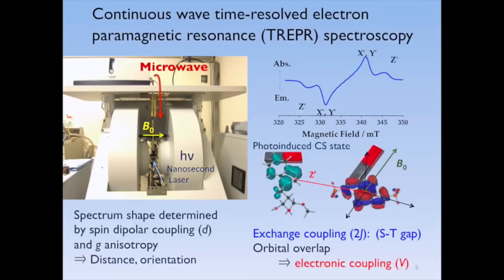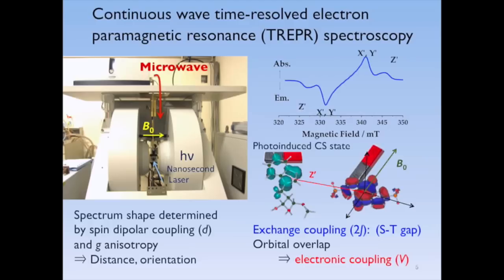The EPR spectrum is also affected by the singlet-triplet energy gap determined by the unpaired orbitals in the charge-separated state. Therefore, from the ST gap, one can determine the electronic coupling of the separated spins. In this perspective, we show that the charge dissociation is exothermic from the contact charge transfer state. This is explained by orbital switching and delocalization by molecular motion in the organic semiconductors. Also, we show that shallow traps are generated in the polymer crystalline phase and play crucial roles for efficient charge conduction at the domain interface.